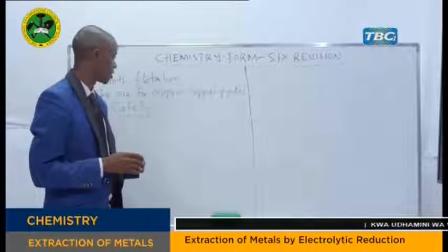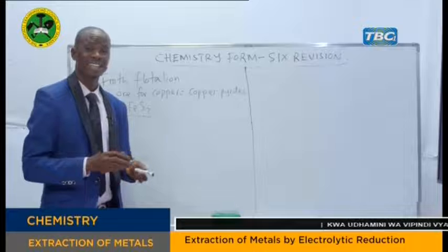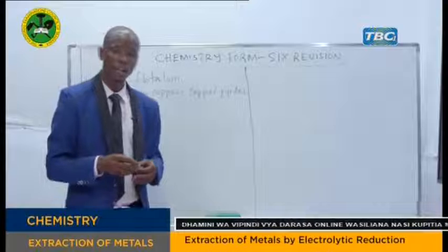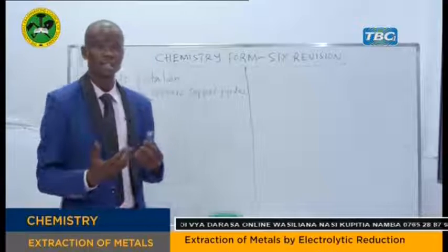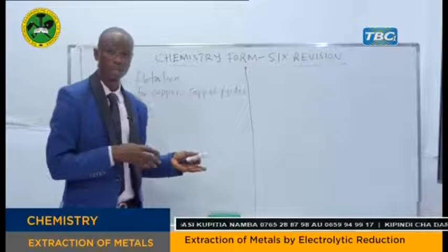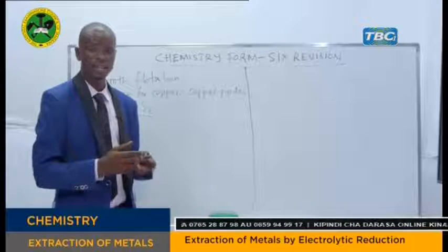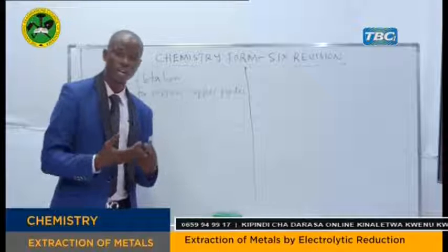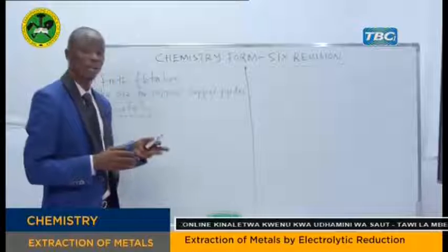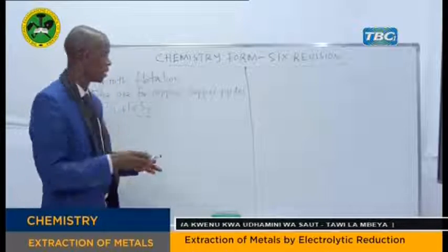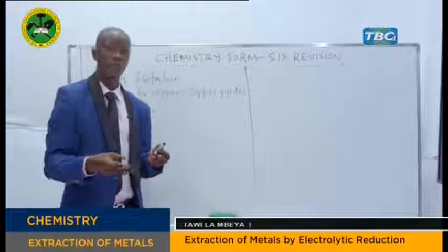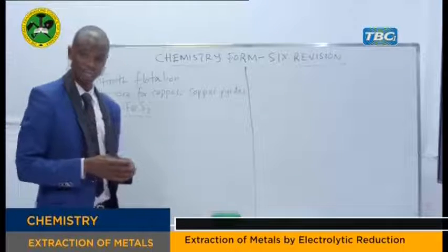So the ore is crushed into powder, mixed with water, followed by the addition of pine oil. The emulsion is agitated by compressing air into the mixture. That causes the oil and the froth to float on the surface along with the ore. So the froth will contain the ore and will be taken for further processing. So that is all about froth flotation.